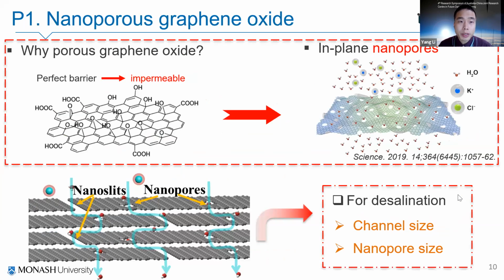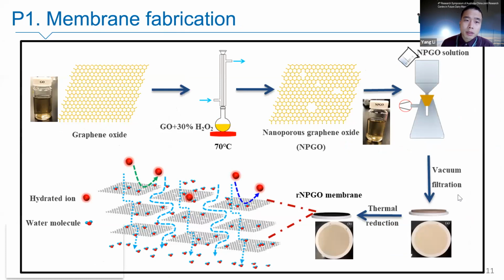So the first project is about the nanoporous graphene oxide. As we already know, the two-dimensional graphene lattice is non-permeable to any water or gas molecules. To use it as a membrane, we introduce nanopores by plasma or some other method. We can create nano-sized pores with precise diameter. If we want to use the laminar membrane for desalination, we have to consider the channel size and the nanopore size as well. The membrane development method is shown here.